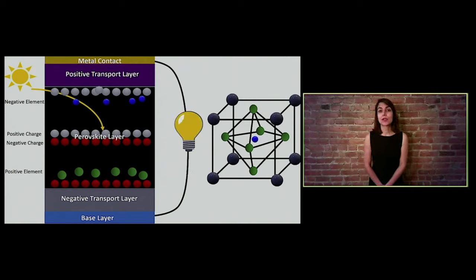This delay that is associated with the transport of negative charge is essentially the root cause of the problem. Because the charges that are trapped at the interface of the perovskite layer and the negative transport layer against their will are going to retaliate by causing some electrochemical reactions and therefore degrading the entire perovskite solar cell structure in about 24 months. What I'm focused on is making a negative transport layer that acts as a highway for the charges and enables them to get out of the system as fast as possible.